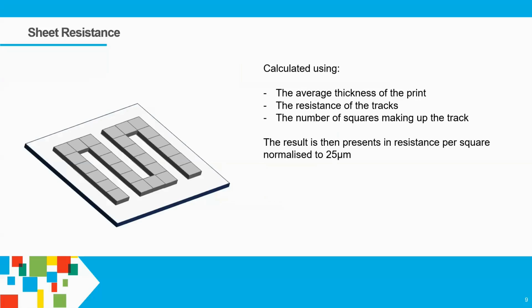Just to give you a brief update, most people know this already. For the sheet resistance, you normally have some sort of meander track. You will have a probe and you'd measure resistance from the entire material. You will measure the thickness of the print, and then you'll work out what the resistance is per what we call theoretical squares of the design. And it's normalized to 25 microns.